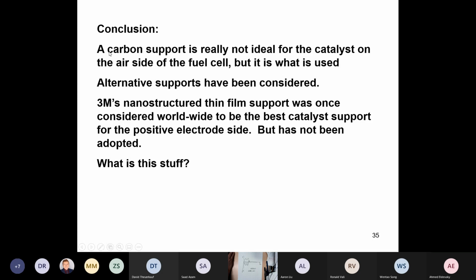Yeah, so a carbon support is not really ideal for the catalyst on the air side of a fuel cell, but it is what's used. And if you think about other things that you might use there, you're about 1 volt positive of standard hydrogen. So it's a very oxidizing environment. Metal supports don't work. They all corrode. Even platinum itself at 1.2 volts, the surface gets covered with platinum oxide, platinum hydroxide. So there's really nothing ideal.